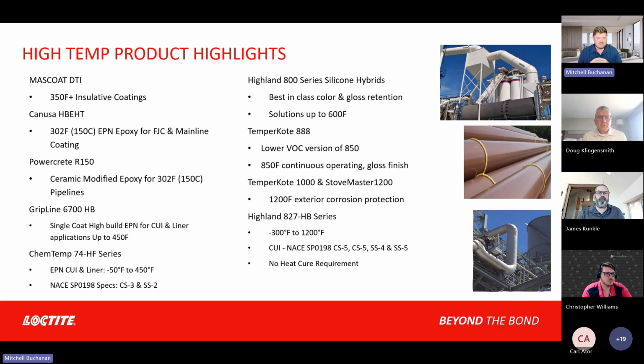And then getting into the TemperKote 1000 and Stovemaster 1200. These are, think exhaust pipes, barbecues, exhaust stacks, things where you have external corrosion, but it's not an extreme corrosion environment. So you don't really need a very high build coating. You don't need two coats, right? So TemperKote 1000 or StoveMaster 1200 are solutions into that up to 1200 Fahrenheit continuous operating.